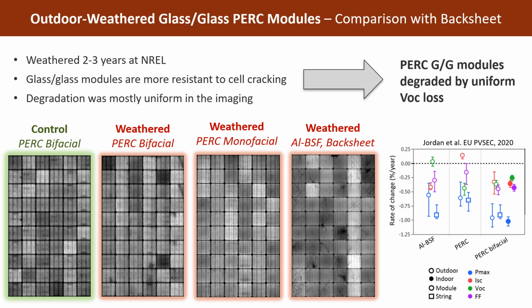The imaging mostly shows uniform EL images that aren't too different from the control, aside from this large amount of cell cracking in the aluminum BSF module. So this is an important indication of the greater mechanical strength of glass-glass modules due to their symmetric and more rigid laminate compared to the glass backsheet module.